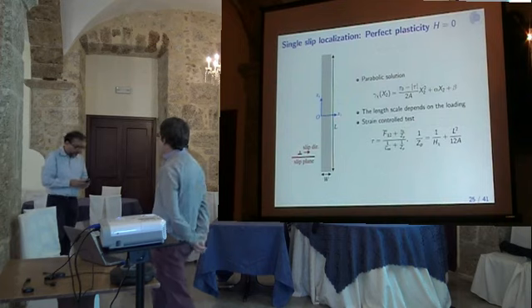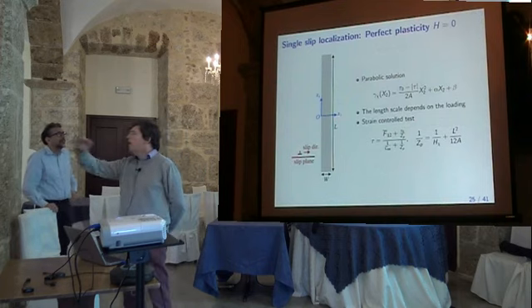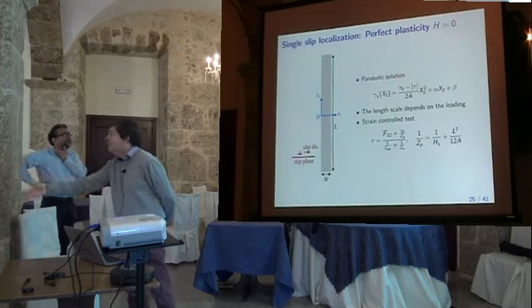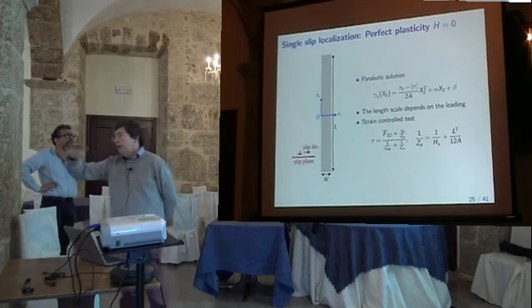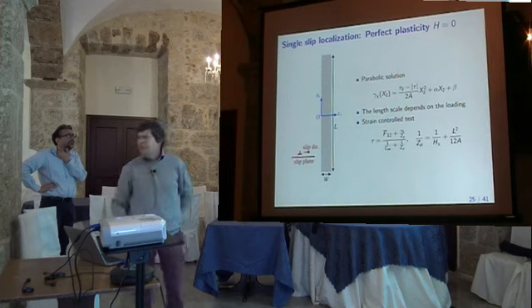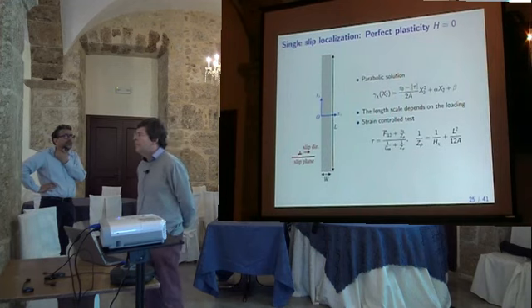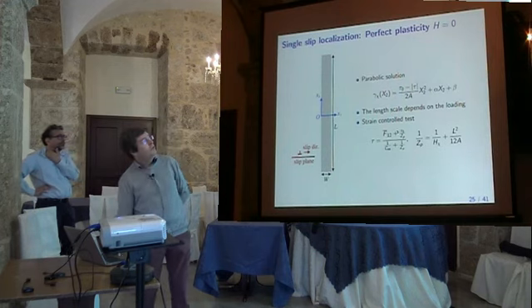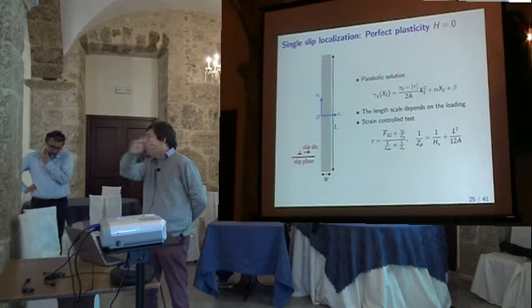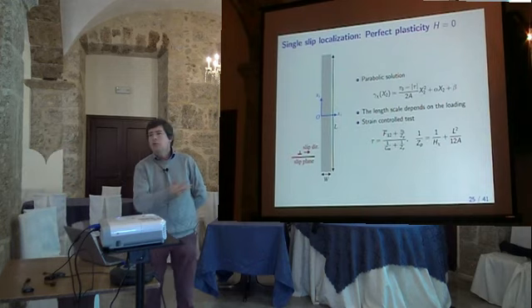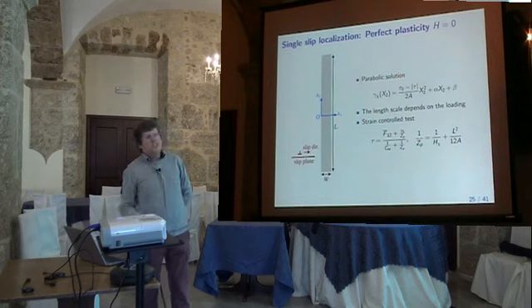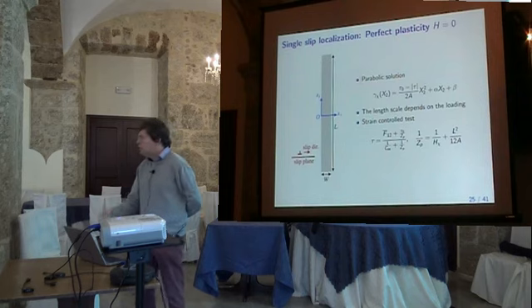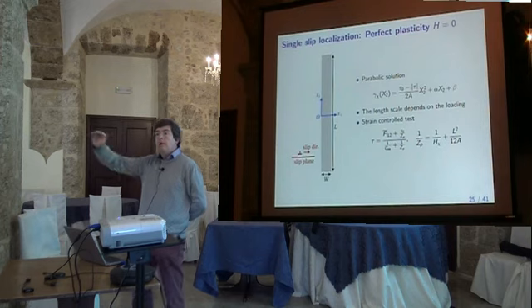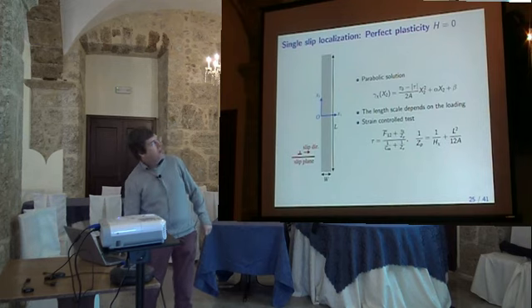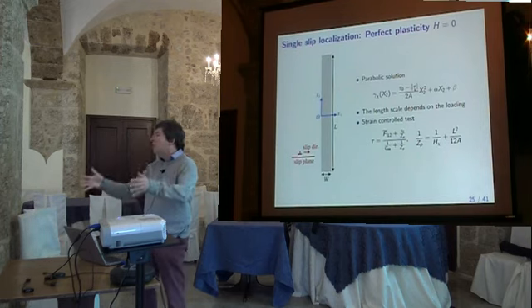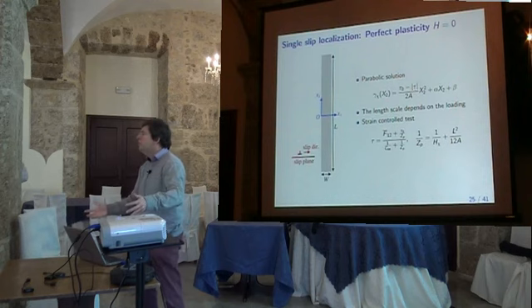Now consider the case H is 0. So you have no hardening, it's perfect plasticity, slip lines as you mentioned earlier, the parabolic case in fact. In that case the solution is different, it's not an exponential function, it's a parabolic function of the position. So you have a band, I will show the profiles, this is a parabolic solution. There is a length scale of course, which is the curvature of the parabola. But this length scale will depend on the boundary condition. This is not an intrinsic one.